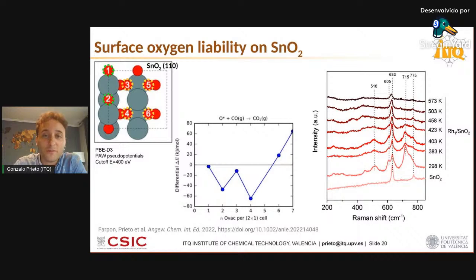This catalyst has a 3 square meters per gram surface area. So we're talking about pretty sintered tin oxide and therefore quite stable crystallite morphologies. There are two different types of surface oxygens exposed on that facet. On the scheme that I'm showing on the left-hand side, those are marked as green and yellow, respectively. The first type of oxygens, two atoms in the unit cell that I'm showing there, are so-called bridging oxygens. Whereas the other four, labeled 3 to 6, are so-called in-plane oxygens.